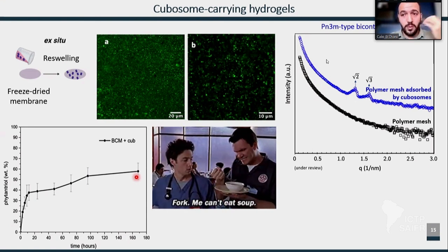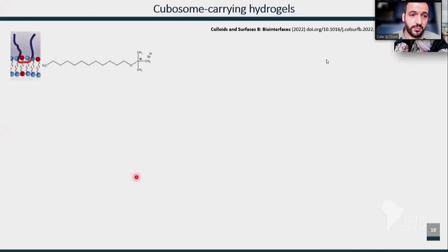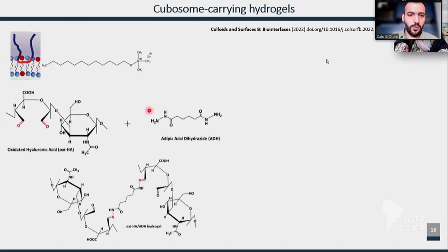So what can we do with electrostatics to prevent that? We switched some of the phytantriol molecules here by cationic surfactants. In this case, it was CTAB, right? So we put positively charged groups on the surface of the cubosome, right? And we oxidized the polymer gel. In this case, it was hyaluronic acid, but we've also done it with cellulose, bacterial cellulose, and we cross-linked. So we have now a big mesh still, but negatively charged, and the positively charged cubosome.